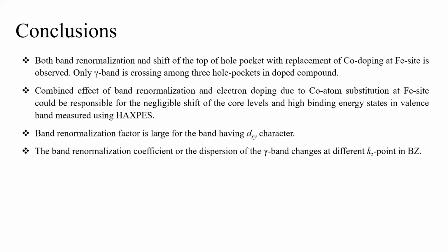Since the gamma band has majorly dxy orbital character, we are expecting that the band renormalization factors are large for the dxy character bands. People have found this in other iron-based superconductors also. Recently, in 2020 I guess, people did measurements on other iron-based superconductors where they found that the dxy character bands show a large renormalization factor. We also observed that the renormalization coefficient varies at different kz values. If you change the kz value, the renormalization factor at some point becomes almost 1, it goes close to the value 1, but at other values it is very high.